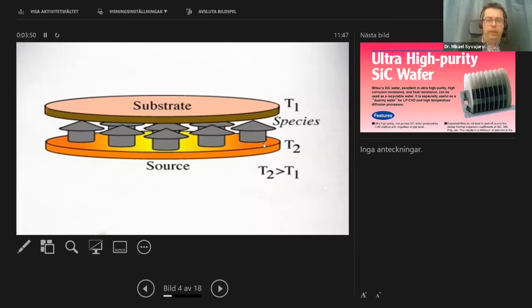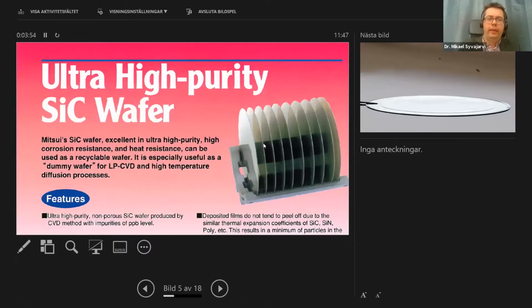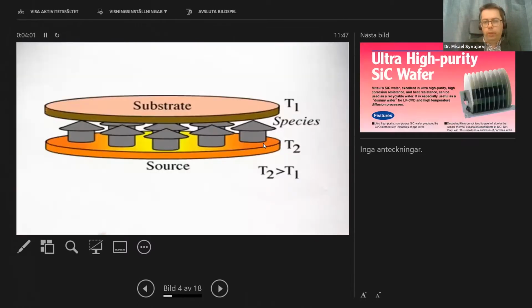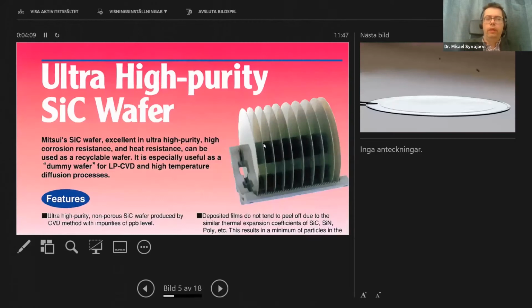So in my PhD thesis work, we used as source material this ceramic silicon carbide. If you look at the bottom here, where it says source, that is a polycrystalline ceramic material, which is available and being used in the industry as a dummy wafer for thermal properties and for high temperature properties, because this is what silicon carbide is good for. So then we are sort of into the ceramics, but we are using this for the electronics thin film growth. So I will come back to this ceramic type of silicon carbide when I talk about the new applications which emerged from this.